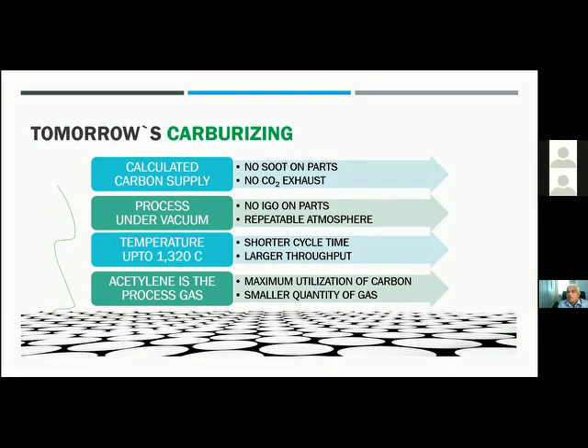Thirdly, because the systems are under vacuum, the furnaces are designed and capable of going up to 1320 C or 2400 F, because typical vacuum heat treatment furnaces for tool steels are designed for 1300 C. So the vacuum carburizing furnaces can also go up to that level, though you wouldn't use it at that level. But it allows you to carburize even the conventional 16MnCr5 and 20MnCr5 steels up to 980 degrees C, compared to the 930, 935 that you would do in a conventional furnace.